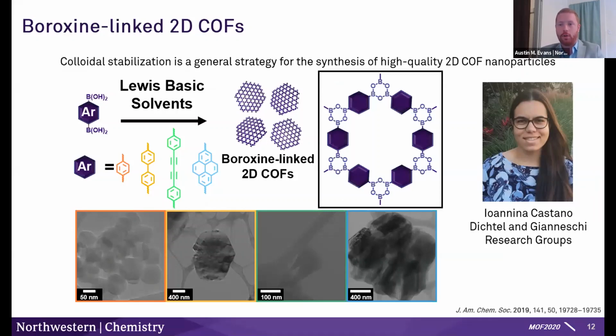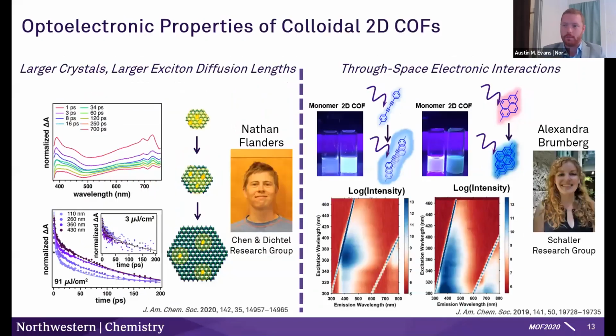And being able to have colloidally stable suspensions where you have a solution processable form of nanocrystallites is really powerful for a lot of fundamental investigations. For example, a lot of spectroscopies benefit from having stable solutions. And just quickly, my colleague Nate Flanders, who's a joint between the Chen and Dichtel groups at Northwestern, has been looking at different particle sizes and the exciton diffusion lengths in them. And it seems like the 50 nanometer crystallites that are isolated in the polycrystalline powder form are too small to really investigate the fundamental exciton diffusion length in that case, because you have exciton annihilation. So for example, if you want to build highly efficient solar cells, you're going to want larger crystalline domains of your particular COF.